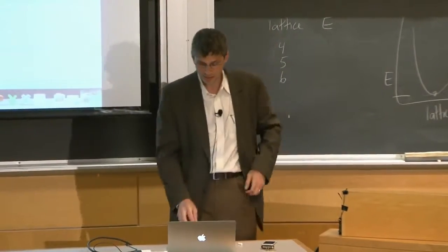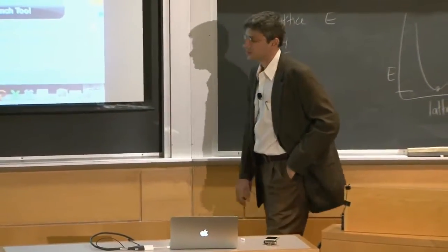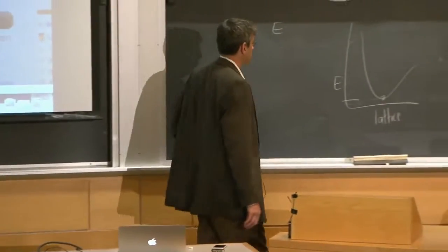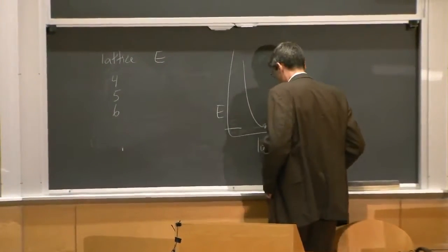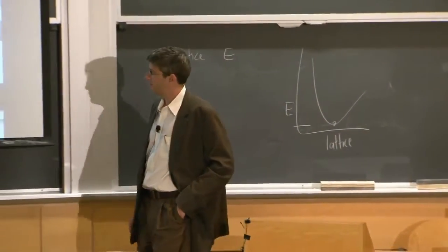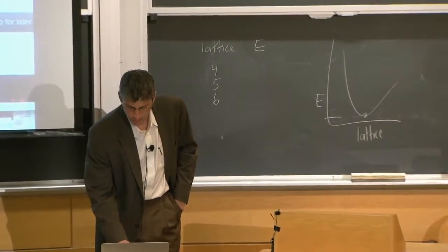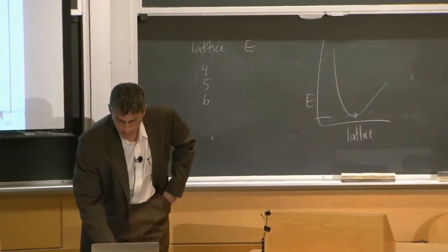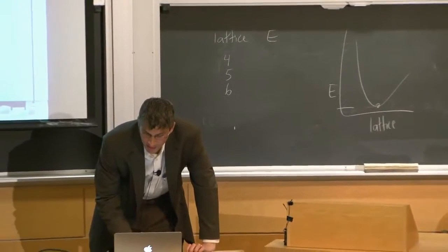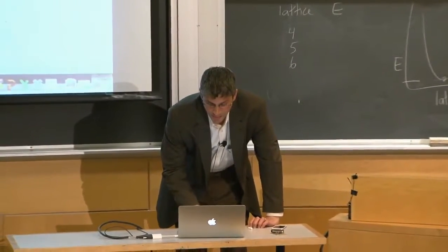Now, if I ask you how to converge the k points for the cohesive energy calculation, how would you do that? I would do exactly what I just did: change the number of k points and see if the cohesive energy changes. And what number of k points is that going to be for the atom? It should be pretty small, probably really just 1, because an isolated atom is not really periodic. If it's really isolated, you shouldn't need more than 1 k point for the atom. But the solid is where you might need to look at the convergence.